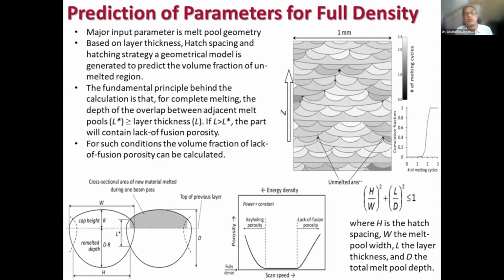Then, in this optimized window, we have to work on hatch spacing. There are models available. Here is one model which is written in Python, which helps us in assessing what the hatch spacing should be with data like melt pool geometry. The gray color in the model gives us a hint: the dark region indicates lack of fusion, but in the light region, melting has happened almost 3 times in the zone. So there are zones where melting occurs more than once, and there are zones where no melting occurs, that is lack of fusion.